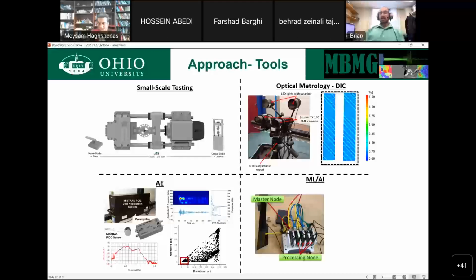And then we apply techniques like optical metrology. Primarily, we do something called digital image correlation, or DIC, which allows us to obtain strain maps as we're applying the load, and acoustic emission. These are primary methodologies. They are not the only ones we use, but through a lot of experience, we found that the surface information from DIC and the volume information from acoustic emission tends to give us a fairly good picture of what's happening without having to put a ton of sensors on this. I'll show you examples of how all of these are used in more detail later.